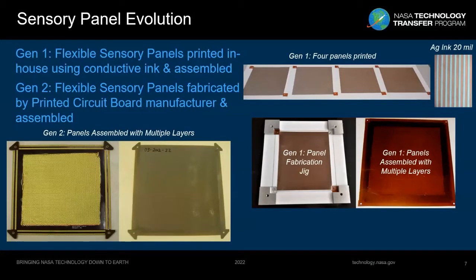And using this technology, we decided to print our first generation of sensory panels. And so on the image on the right, you see the Gen 1 is 4 panels. That's actually a silver-based conductive ink that is printed onto a polyimide substrate using a HP inkjet printer, a color inkjet printer. There's also a little photo to the right that shows what the silver ink traces look like. They're about 20 mils and 20 thousandths of an inch in width.